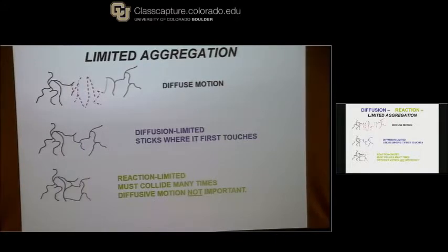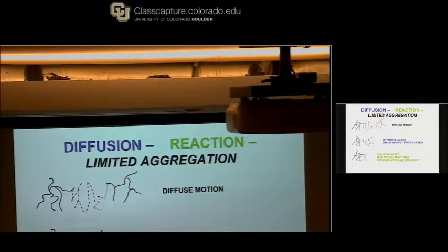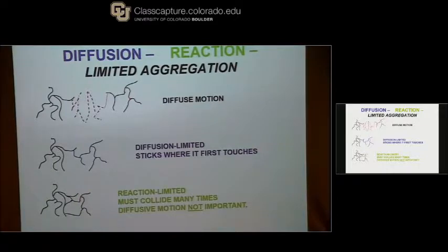And so the difference is, in the first case, whenever the particles hit one another, they immediately stick. But if I put a little bit of a stability barrier, so let's say it takes 1,000 or 1,000,000 times before they actually stick, they're not really stable, but they're quite stable. Then they're diffusing. If something's diffusing, even a single particle, it only sticks to the outside.